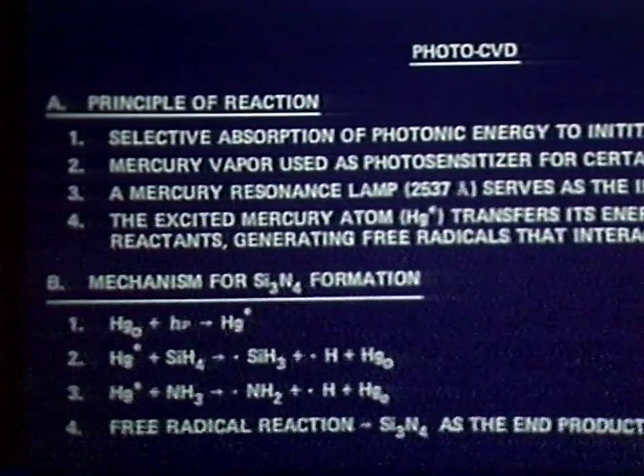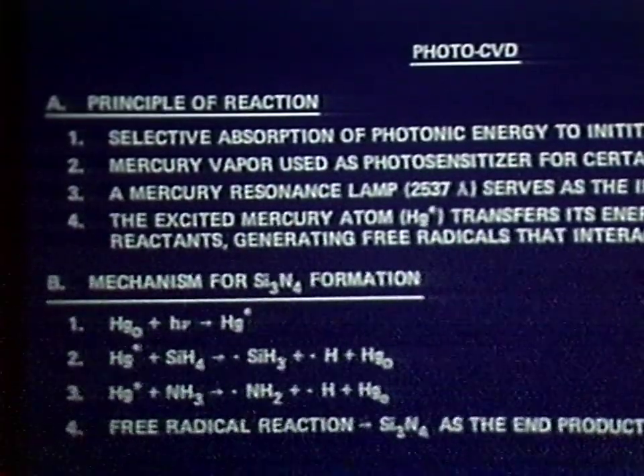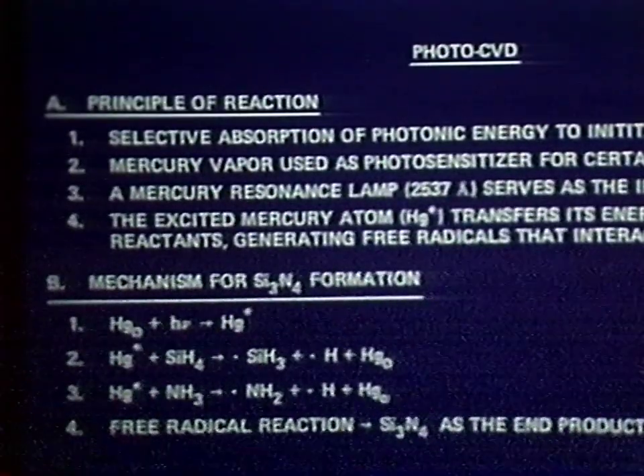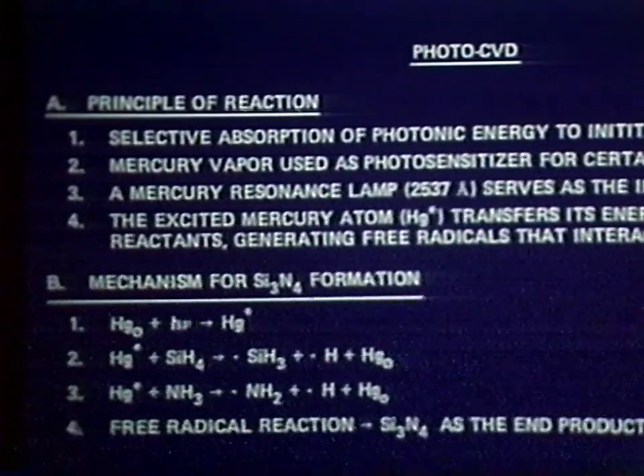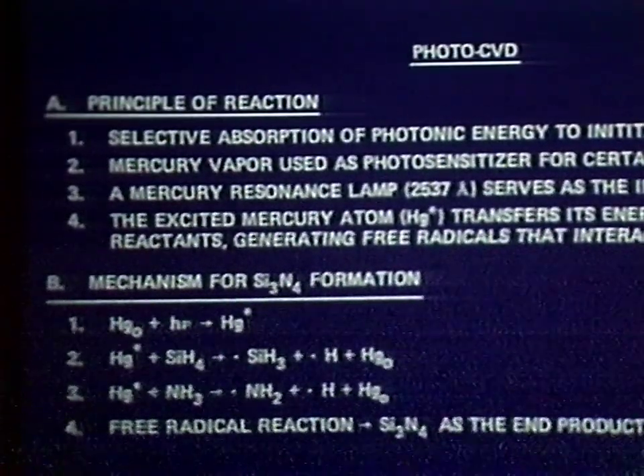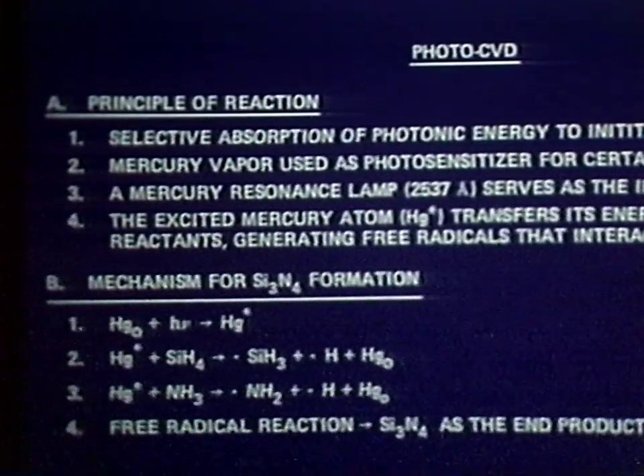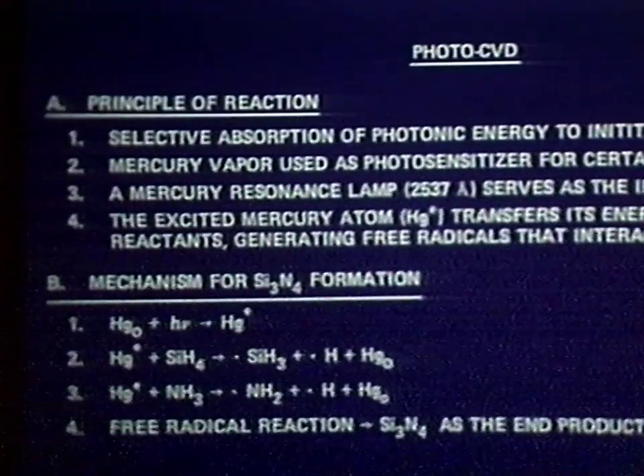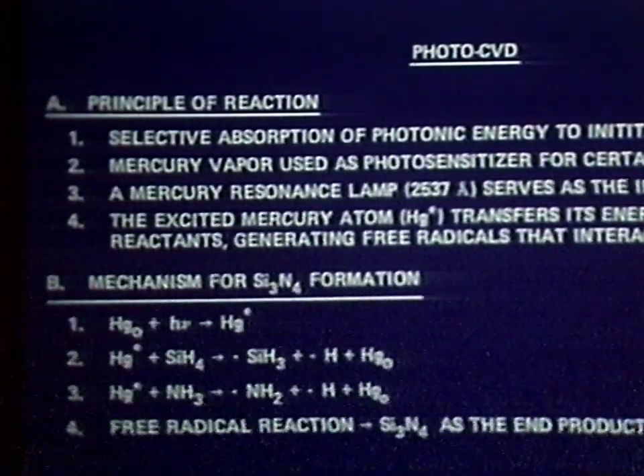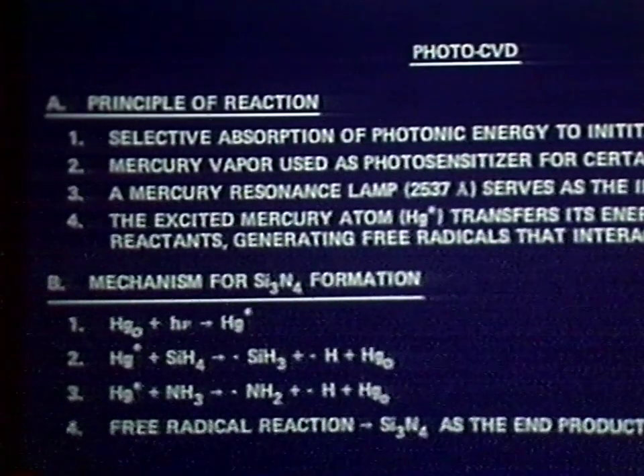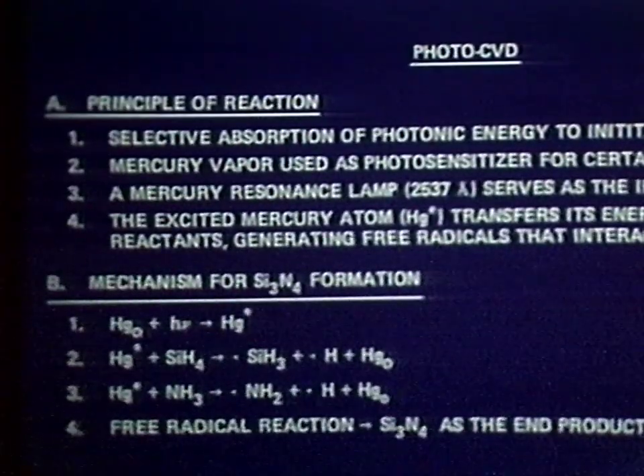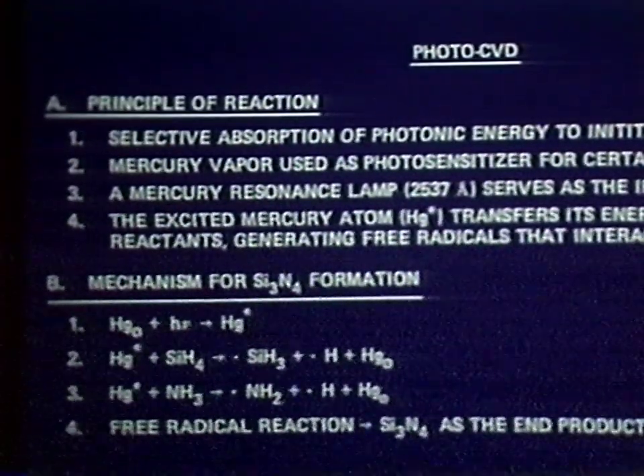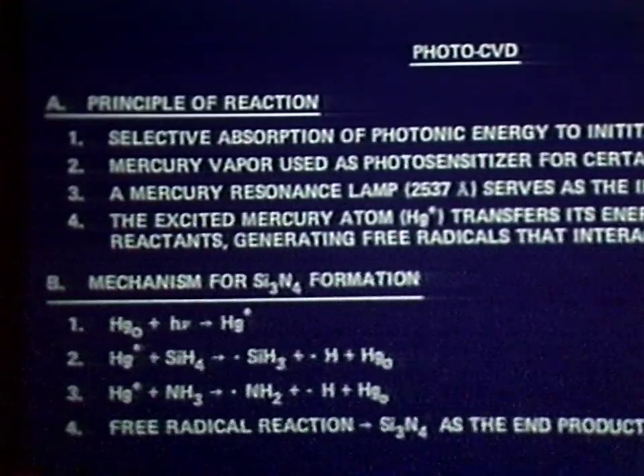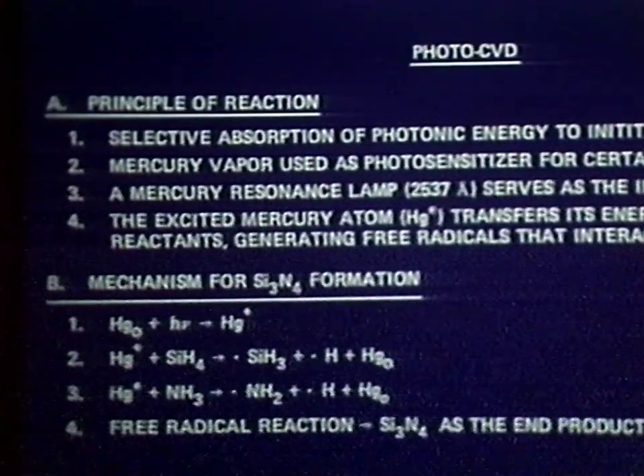Now, another reaction type, another technology really, is photo-CVD. And here, the principle of reaction is the selective absorption of photonic energy to initiate deposition processes. In many cases, mercury is used as the transfer agent of energy. Mercury vapor is used as the photosensitizer, for example, for certain gas-phase reactions. In this case, a mercury resonance lamp is used, which operates at 2537 angstroms to serve as an irradiation source to activate the mercury from the ground state to the excited state, which then transfers energy by collision to reactants in the gas phase and produces various types of films.